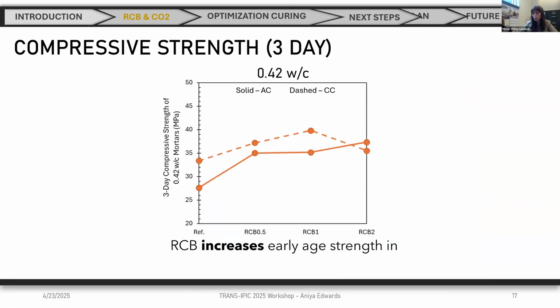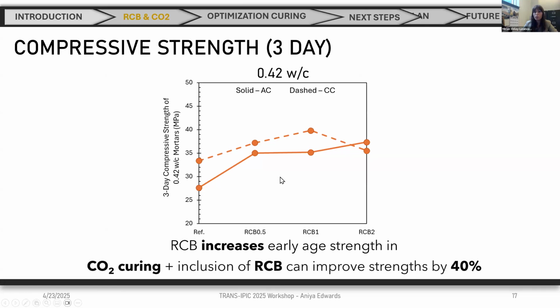And what I want to do, just to share with you some of this data, is show that first, if we focus only on normal curing, meaning no CO2 curing, we can see that the use of carbon black increases the 3-day compressive strength, which is great, right? Because we wanted that. Now, in addition to that, when you do CO2 curing, you will see that you have an increase. The increase is not as big with recovered carbon black, but you are exceeding the one that is just reference and CO2. So what we are seeing is that if we combine CO2 curing and recovered carbon black, we will get the highest value, especially with 1%.